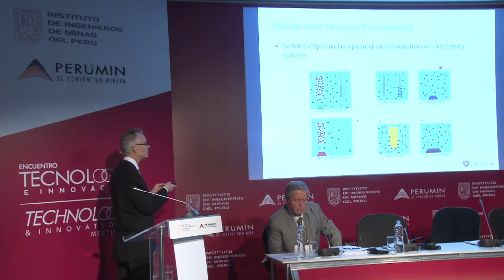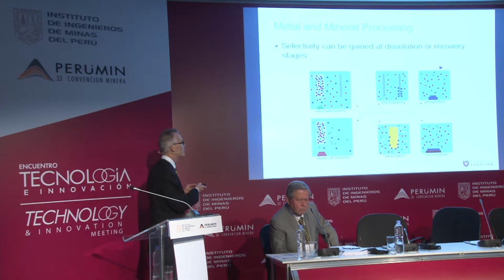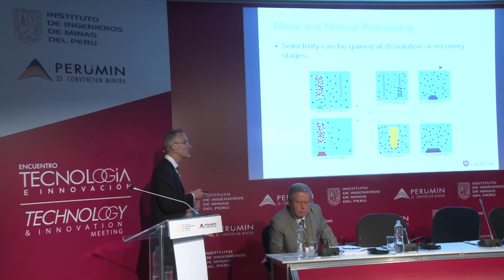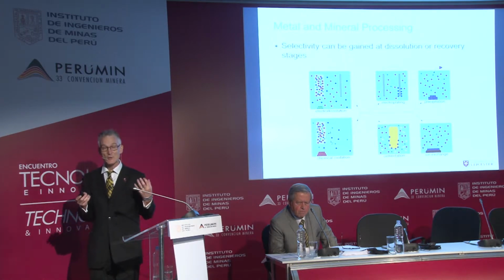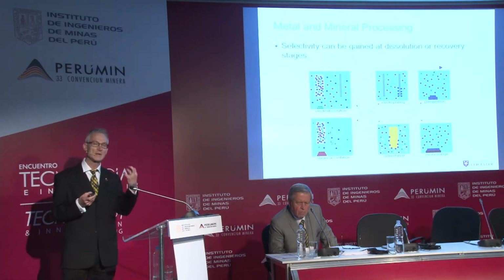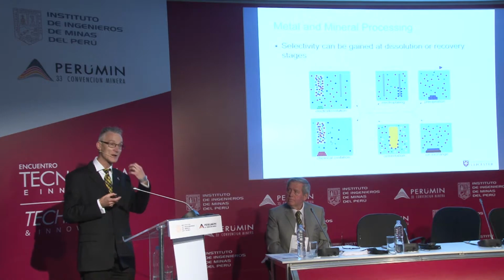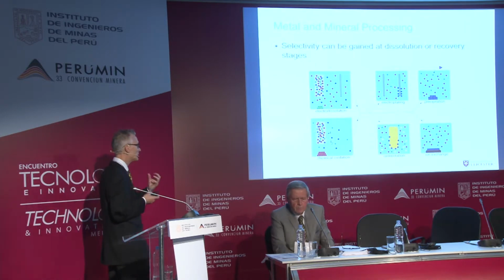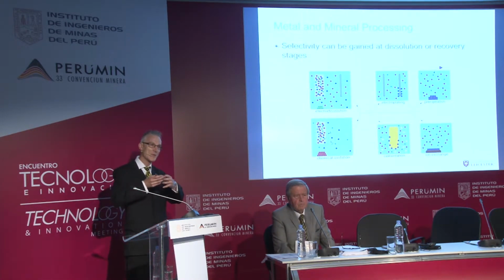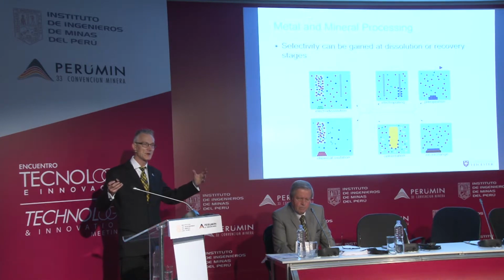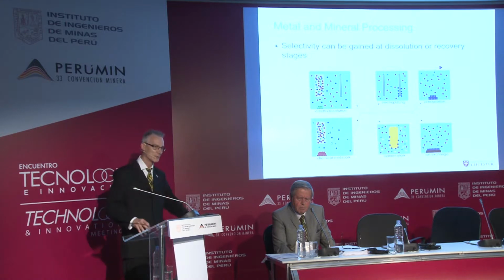Once it's in solution, we have various modes for recovering it. We can electroplate it out. We can co-precipitate it with something else. We can put in a more reactive metal and cement, or we can use ion exchange. Or alternatively, there is a fifth option where we can actually add water because our ionic liquids are completely miscible with water. We can add water and make it become an aqueous system, and then those metals that are not soluble in an aqueous system precipitate out.